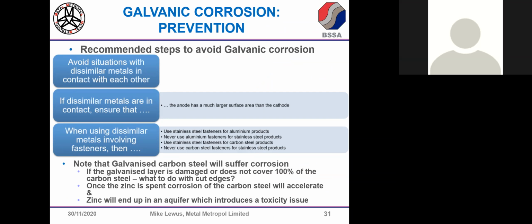I've already mentioned some of the ways of avoiding it, but there's just a footnote here about galvanized steel, which will suffer corrosion too. Many will appreciate the zinc on galvanized material is there as a sacrificial anode. It corrodes at the expense of the steel it's covering, usually plain carbon steel. But if it's damaged, there'll be a local area where it's not protecting the steel. Or what do we do with cut ends? Often galvanized material is cut, and we can paint it, yes, but paints themselves can degrade.